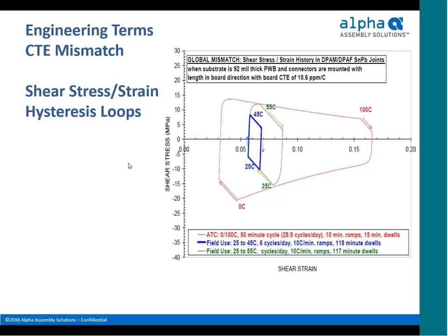And then compare that to the red box, which is the 0 to 100 C with different cycle parameters as far as speed and the up and down direction for temperatures. You can see how you get a much wider range of stress and strain that's applied to the assembly with the larger difference in the hot and cold stages of the thermal cycling. So what this is trying to show you is that it's an exponential increase in the amount of stress that's applied when you get changes in the hot to cold cycle on the temperature thermal cycling specifications.